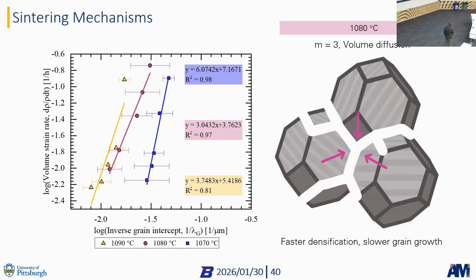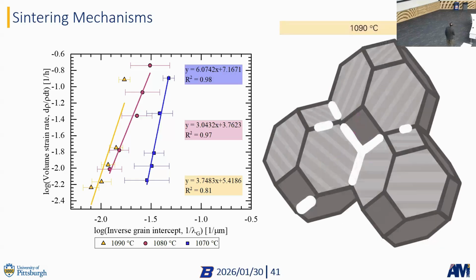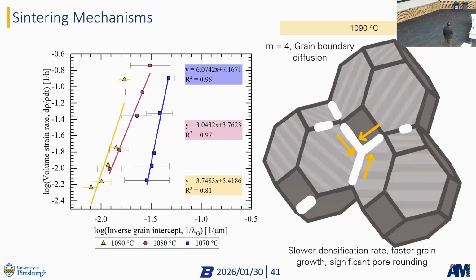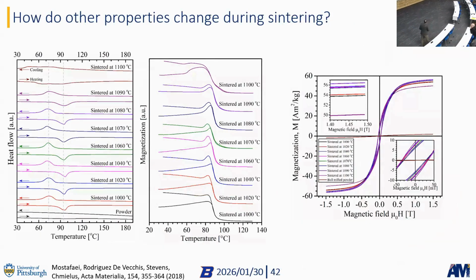The slope here is a 3, which indicates volume diffusion. So we have a faster densification rate and slower grain growth. And for high temperatures, we get grain boundary diffusion, which means a slower densification rate, faster grain growth, and significant pore rounding. So instead of elongated pores, we actually see round pores. What was really cool about this is that all the functional properties that we measured before stayed the same, except for 1100 degrees C.